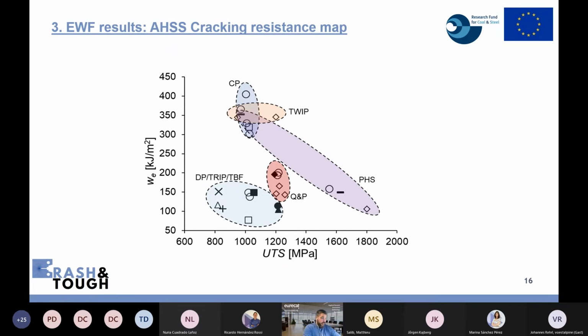Here also, as an exercise, we wanted to put all the values of the essential work of fracture in the classification map that I showed in the previous slide. And we can see more or less where they fit. The 780 steels, the DP and TRIP, are more or less in the same group of similar steel grades. Regarding the DP 980, you can see also the DP 980 from Stelpin, more or less with similar values to other dual phase steels with similar strength level. In this case, we could also observe this very high fracture toughness for the DP 900 from Arcelor, which is closer to other complex phase steels.